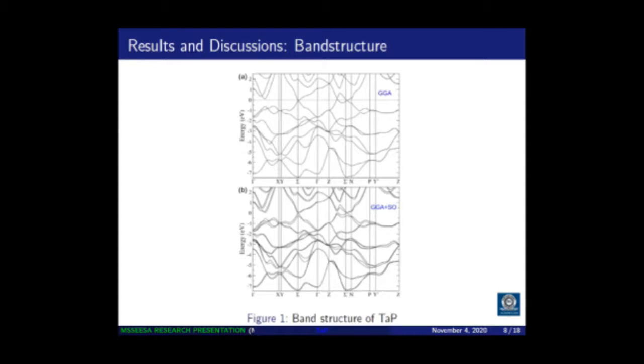Now I applied the spin-orbit coupling so that I can see how this particular system behaves. And as you can see in the second figure, after applying the spin-orbit coupling, there is something happening in this structure. One, you can see that there is an energy gap at this particular point, and this is a result of applying the spin-orbit coupling to the system. Then another thing you can observe in this band structure, in this region, there is a band inversion occurring, and it's the effect of the spin-orbit coupling. And another one is that these bands are splitting. That means when we apply the spin-orbit coupling, it also has the effect of splitting the bands, what we call the double degeneracy. And move to the next.